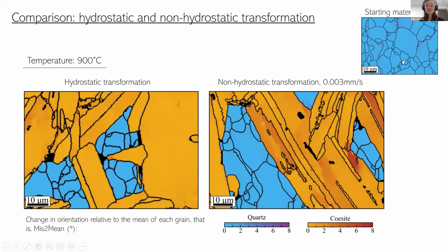So we can do that again using EBSD data, but in this case, we're using something called Mis2Mean. What that does is it takes an average orientation of each grain, and then it calculates for every single pixel the misorientation of that pixel comparative to the average orientation. Because we're looking at samples where we're trying to identify this transient weakening as you're deforming it, we need a null hypothesis or something to compare it to. So we did a load of experiments under what we call hydrostatic conditions. So this is where we're not deforming them as we go through the transition. And up on the right, you can also see our starting material, which is just the quartz microstructure.